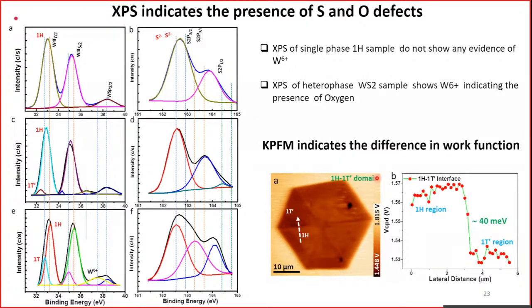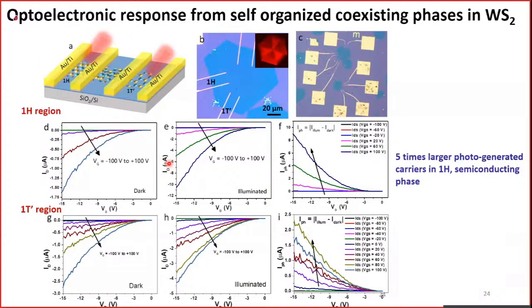We also looked at KPFM because we want to know the surface contact potential properties. Is there any difference we could observe? Again, we are observing around 40 milli-electron volt of contact potential difference between your 1H phase and 1T prime phase. We made a transistor, and more importantly, in a transistor, we want to see the photoconductivity, especially if you want to make photodetectors and so on. We want to have a good semiconductor. So in this case we have done photodetector or photoconductivity measurement from one flake.